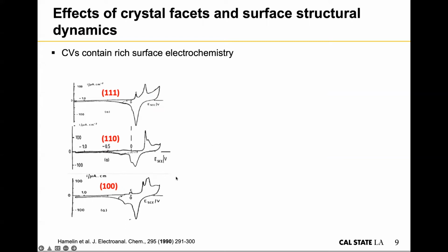So for example, this paper talks about using single crystal electrodes with 111, 110, or 100 different types of surface. You can actually get different minor peaks in a CV. And those different minor peaks can be used to identify different types of surface. So what we have been trying to do for a long time is whether we can get a nanoparticle electrochemistry CV, and from that specific CV, look for those identification fingerprints that correlate to the surface facets, so we don't have to do a TEM or other technique for identifying the surface structure.